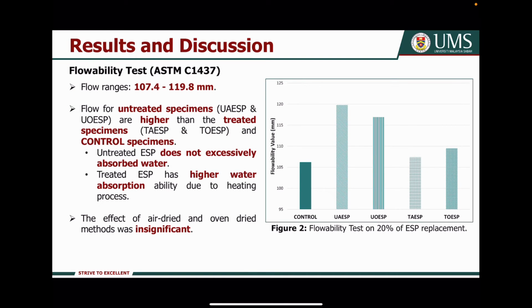For the result and discussion of the flowability test, as you can see in the figure, the flow of the untreated specimens is higher than the treated specimens and control specimen. This is because the untreated ESP does not excessively absorb water, meanwhile the treated ESP has higher water absorption ability due to the heating process. Meanwhile, the effect of the air-dried and oven-dried method was insignificant.